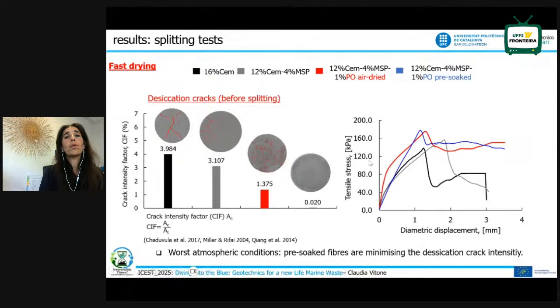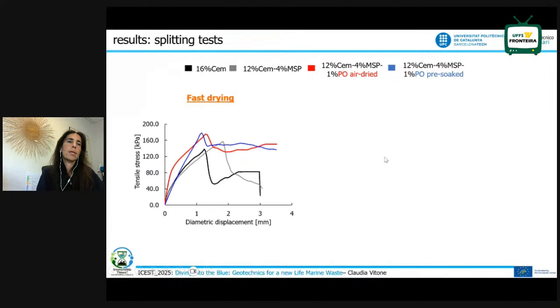And this is also reflected in higher tensile stress when we had the fibers, since the material was practically almost not cracked. Instead, as you can see here, on the highly cracked material, that is the one with the cement and sediment, we have also lower tensile stress.